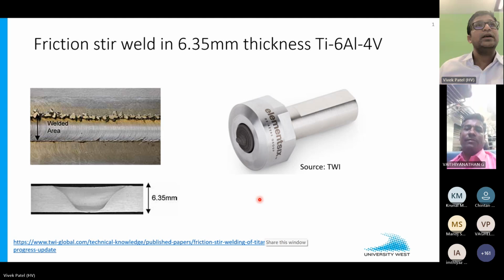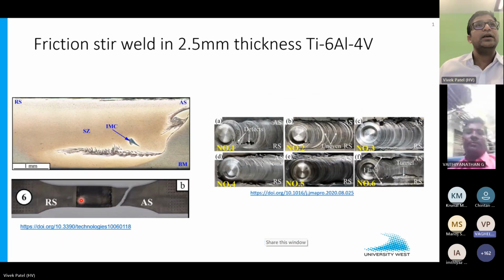in some matrix. You can see some recent applications of a 6.35 millimeter thick titanium butt joint, and it's a beautiful cross section of such a hard material, and you have very fine grains, of course. If you weld by fusion methods, then you have a columnar structure for this material. And also in small thickness.